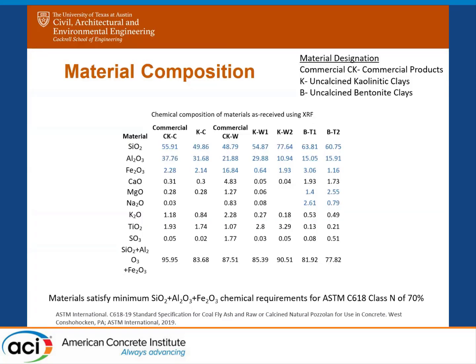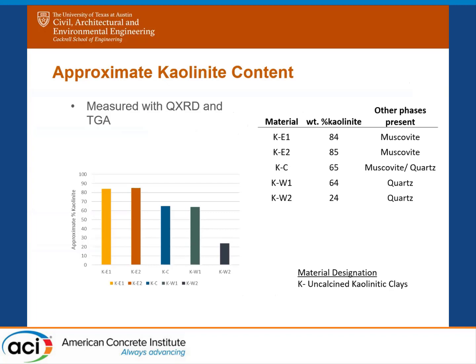So just a brief material composition by XRF. All of these materials satisfy the chemical requirements for Class N of ASTM C618. And with that, one important thing is kaolinite content for these clays and their influence on reactivity. So the goal was to obtain a wide range of kaolinite contents. And we did do that, from 24% all the way up to 85%.